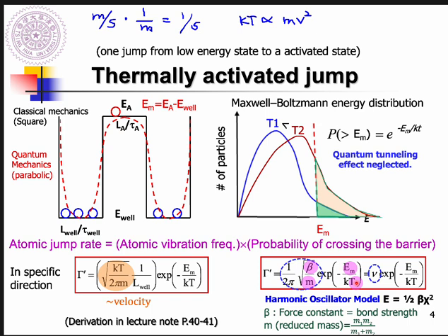So if you want to increase the jump rate, you can either increase the bond strength, reduce the atomic mass, or lower the migration energy, or increase the working temperature. This is what you can do. It turns out you can speed up the diffusion phenomena, right? So this is gamma prime. Okay, in the following slides, we are going to use this model to interpret the gamma